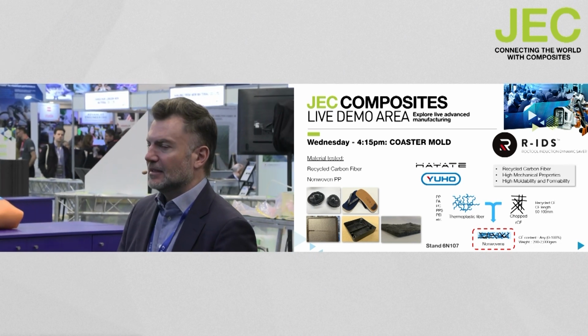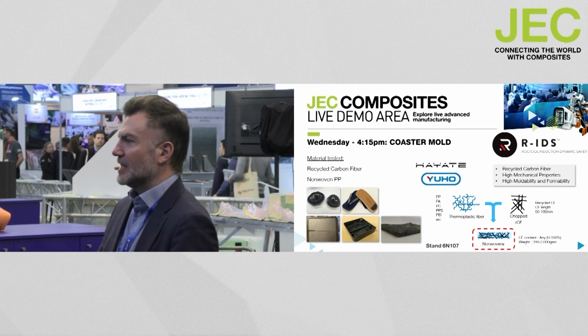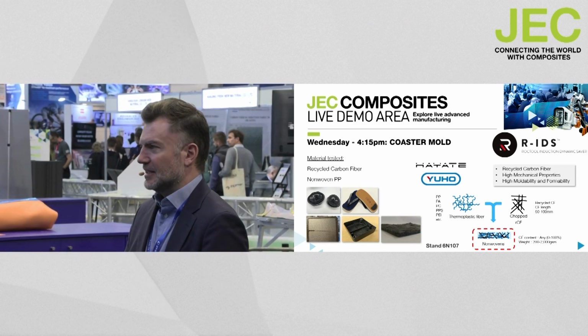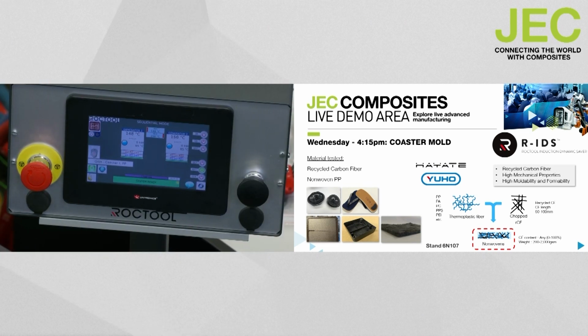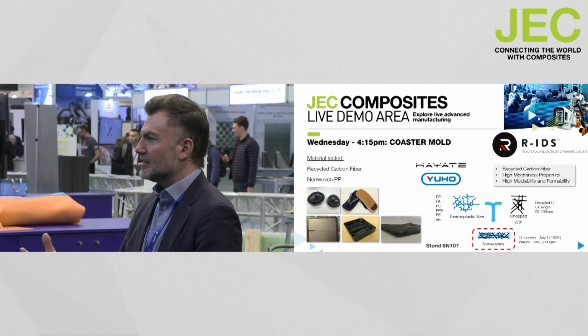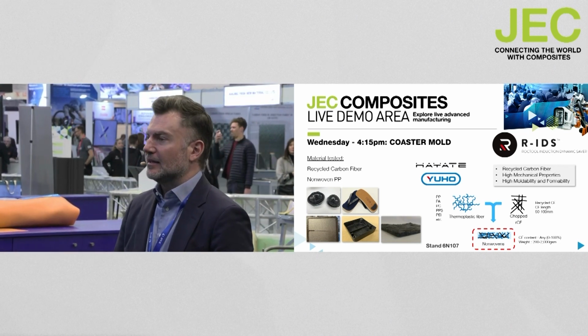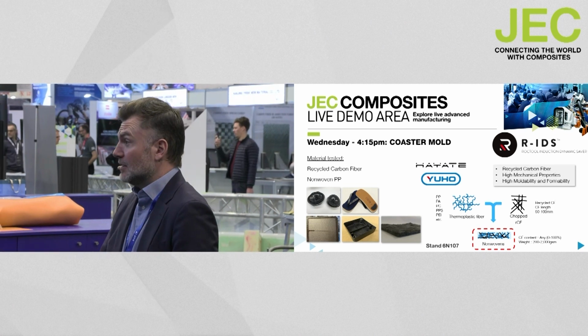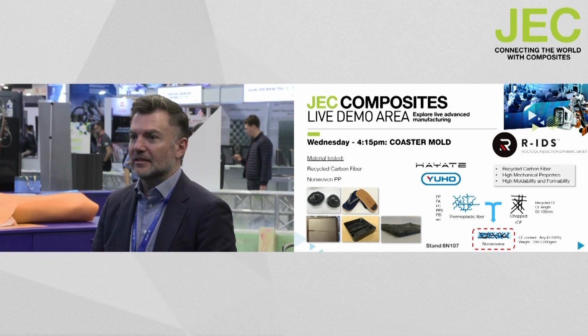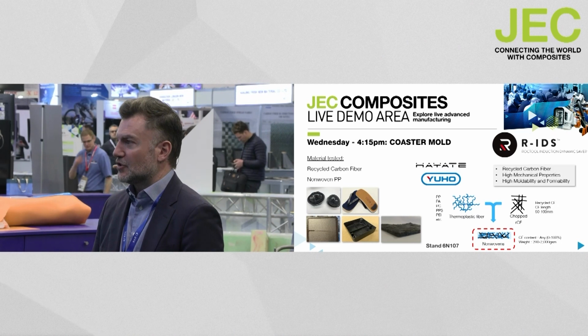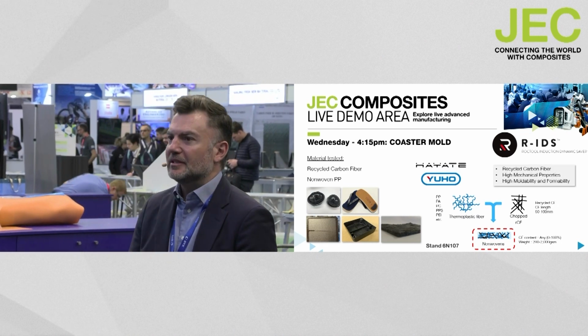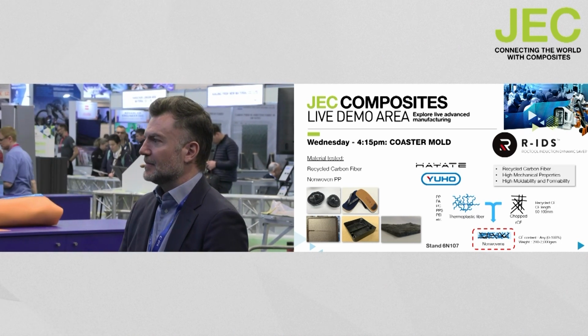Induction, 200 or 250 Celsius is actually low heat for induction. For a lot of manufacturers, 250 already raises the question of what kind of system to use. With induction we can go 350, 400 plus. We have projects with PEEK or PPS and other PEI, also high heat resins that require that level of temperature. So induction gives you this flexibility in the temperature that you can reach.